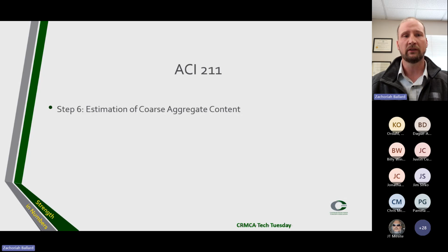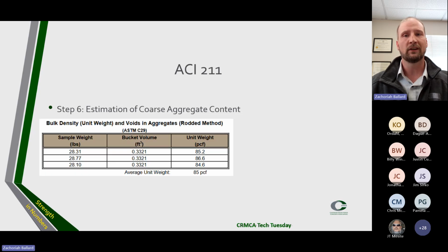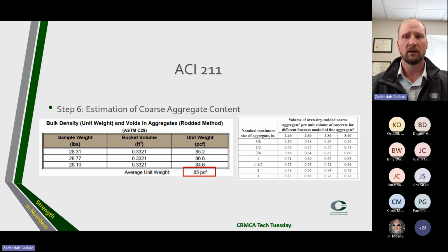So our step 6, estimation of coarse aggregate content. Aggregates of essentially the same nominal maximum size and grading will produce concrete of satisfactory workability when a particular volume of coarse aggregate on an oven dry rodded basis is used per unit volume of concrete. The appropriate values for this aggregate volume are given in table 6.3.6. Bulk volume of an aggregate needed, we're going to use that 3/4.